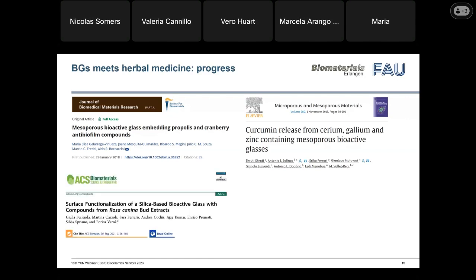Then in another study, they considered the functionalization of mesoporous-derived glasses with compounds of Rosa canina bud extracts. Here it was quite interesting what they did at the beginning, because they made a surface activation. This was to expose the hydroxyl groups on the surface, so that they could have a better attachment of the plant-derived compound. And this was done due to the anti-inflammatory and antioxidant properties of these bud extracts.